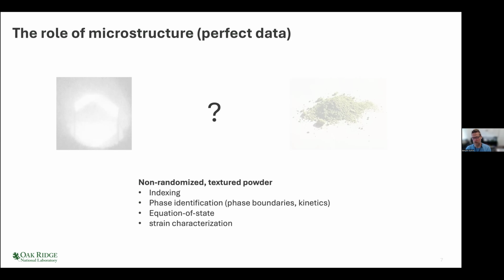You can actually do a lot. So you can still index in a lot of cases. You can identify phases and you can track them. So look at phase boundaries, look at kinetics. You can measure equations of state, and you can even look at strain in the lattice by looking at the widths of the peaks. But there's some things you cannot do. You essentially lose all information on the crystal structure, and that means quantitative analysis of mixtures and phase transitions is no longer possible because the information is not in the data.